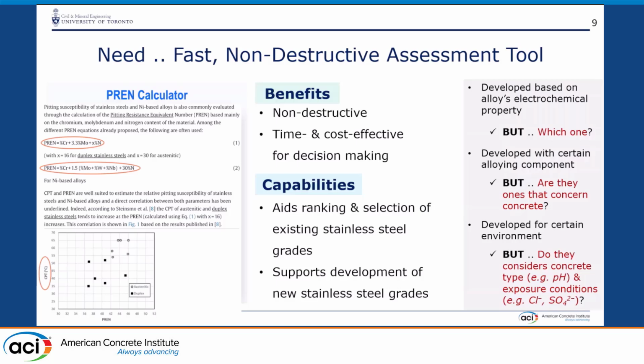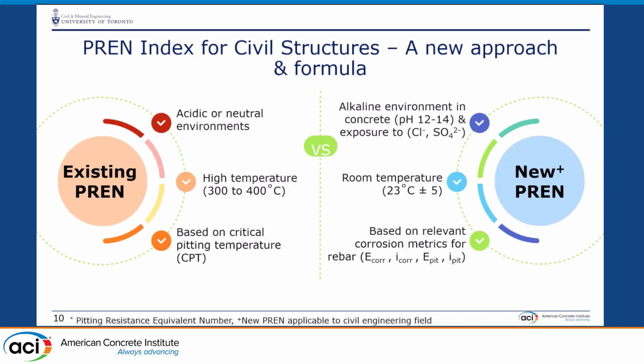And if we're trying to solve the cost effectiveness of stainless steel, we need to look at the expensive alloys, molybdenum, nickel, etc. The other thing is it doesn't actually capture our exposure environment, so the current PREN number is not going to work. So looking on the right-hand side is what we're proposing. As I've said, the existing one is for acid to neutral environment, 300 to 400 degrees Celsius temperature. And we're proposing something that actually fits the high pH as opposed to neutral environment, so 12 to 14 pH, and presumably lower too if time permits.